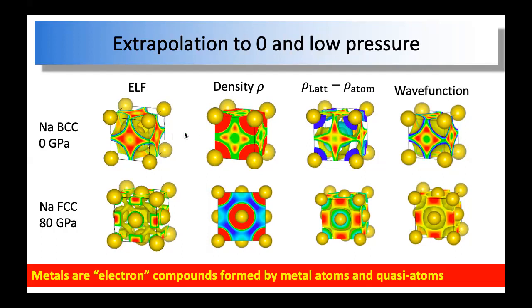If you look at the density, it is very, very uniform. However, if you tune it very carefully and magnify the difference between the maximum point and neighboring points, you do see a little maximum, although the difference between this point and this point is very, very small. It's very uniformly distributed. But if you amplify that, you can see that there's indeed a maximum here. And if you subtract the individual atom densities from the density of the whole lattice, then you can clearly see the maximum here. That means the electrons will flow into here. If you start from the single-atom density for each sodium and then let it go into the same lattice, the electrons will flow into this region, in other words, occupying this state, which we can also assume to be a quasi-atom orbital.